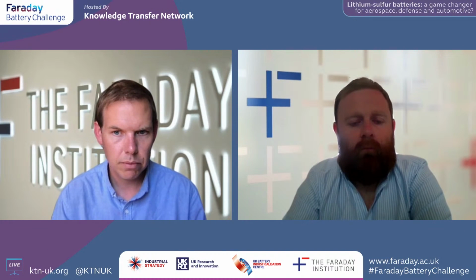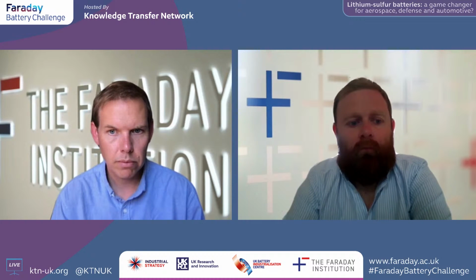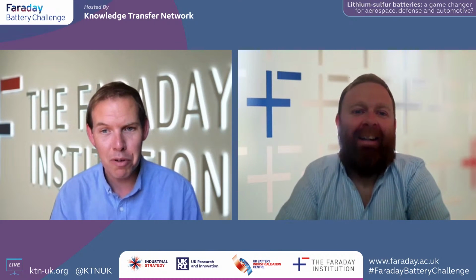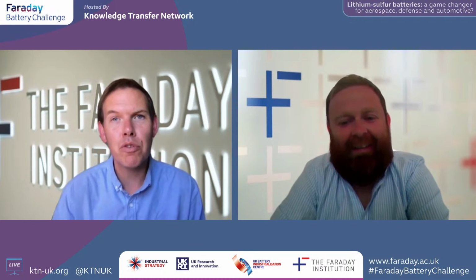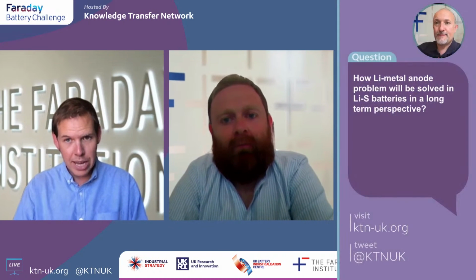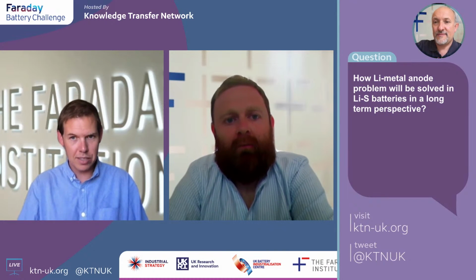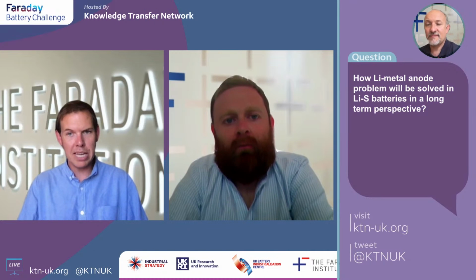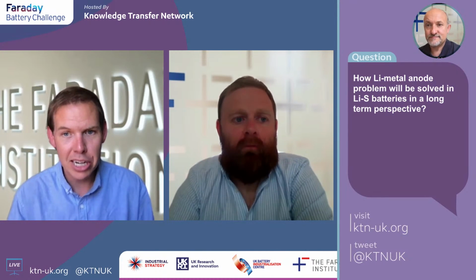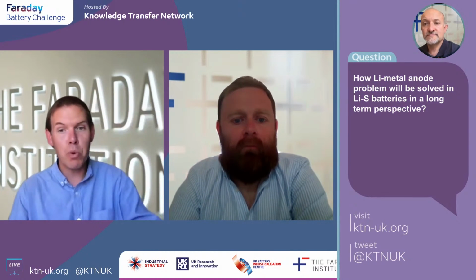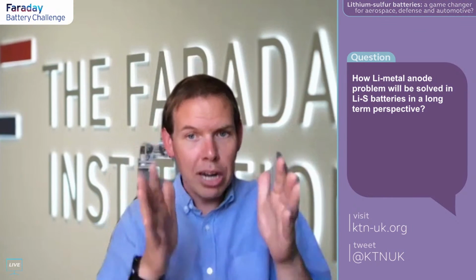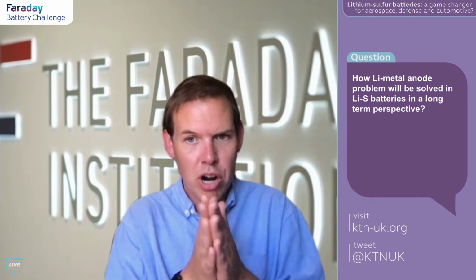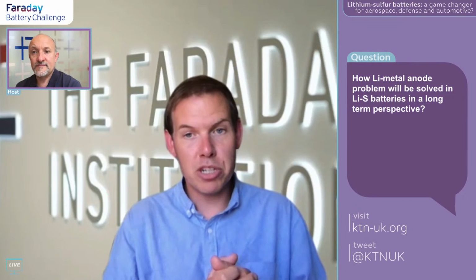So when we've got lithium-sulfur cells, lithium anodes is one of the things that we're looking for. So how close do you think we are to solving the lithium metal anode problems? Good question, and I could probably wax lyrical for about an hour and a half about that. I'll try and keep it brief. I think that for a range of next generation battery chemistries, employing alkali metal electrodes is often seen as the kind of holy grail. I think that when you look at the solid state battery community in particular, it's a lot more difficult than people initially thought. If we take solid state batteries as an example, it was always expected that below critical current densities, the solid electrolyte would block the penetration of lithium dendrites during charge and discharge. And obviously over the past 10 or 15 years, that's been shown not always to be the case.